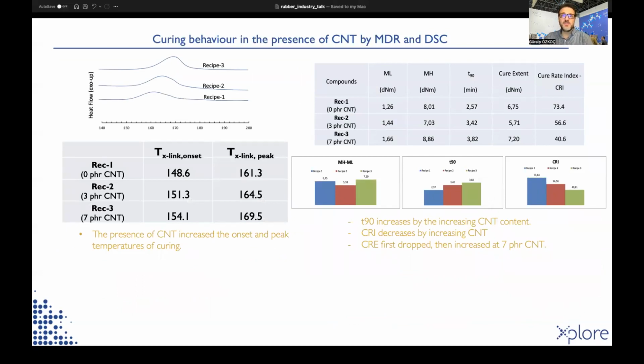The existence of high aspect ratio fillers like carbon nanotubes is known to be effective in the curing behavior of rubber compounds. In order to check this, we performed moving die rheometer analysis and DSC experiments. We observed from DSC that the presence of carbon nanotubes increased onset and peak temperatures of the curing exotherm, as you can see. In other words, it results in a delay in curing behavior. This can be due to the barrier effect of carbon nanotubes against the diffusion of reactive groups that sustain the vulcanization reaction. A complementary behavior was also observed from moving die rheometer results, indicating that the cross-linking reaction was retarded by the presence of carbon nanotube.